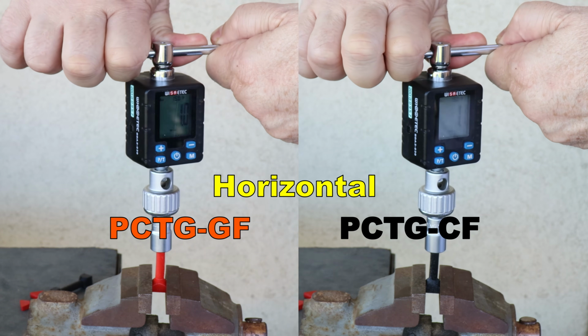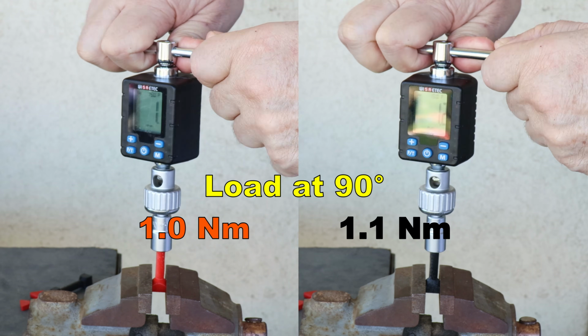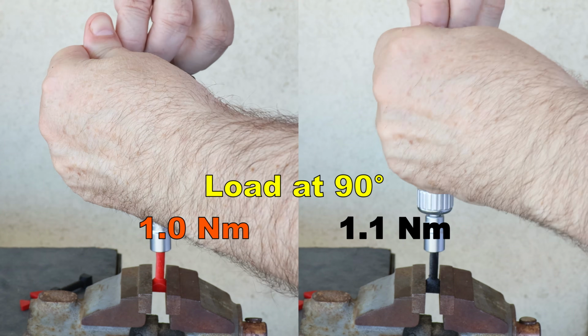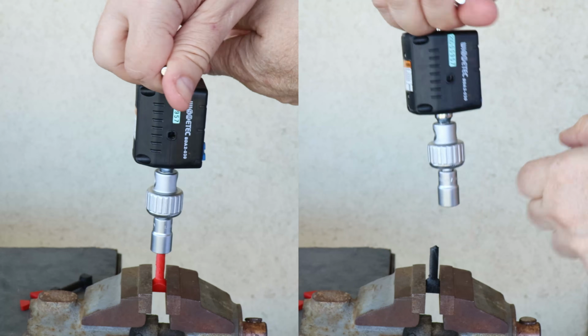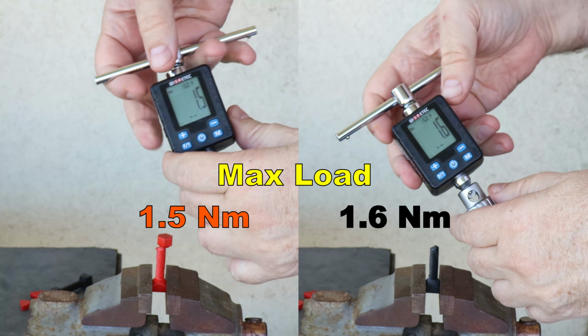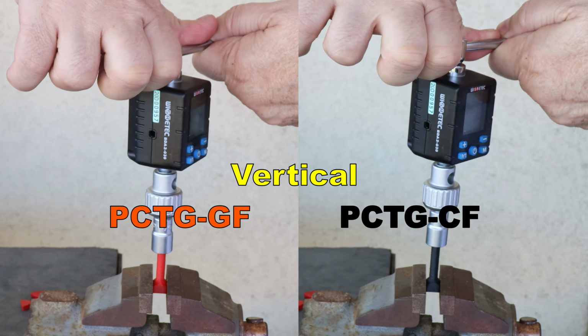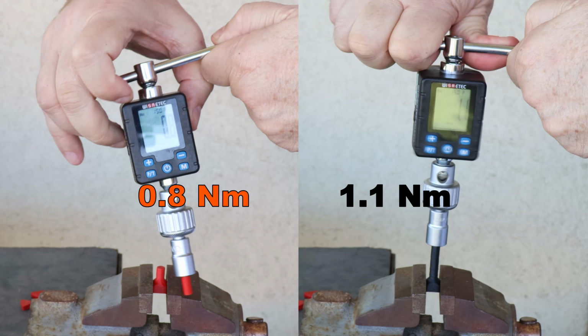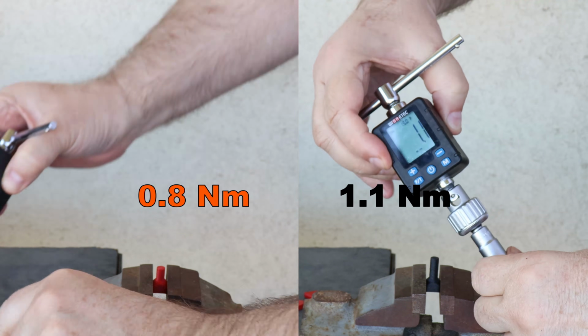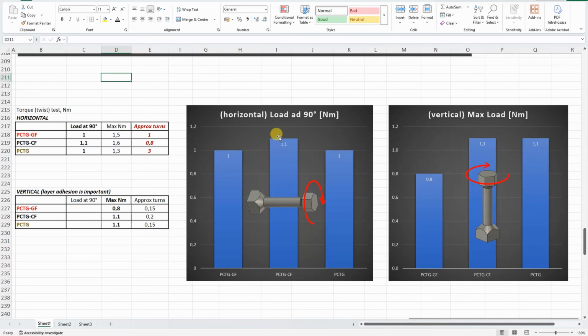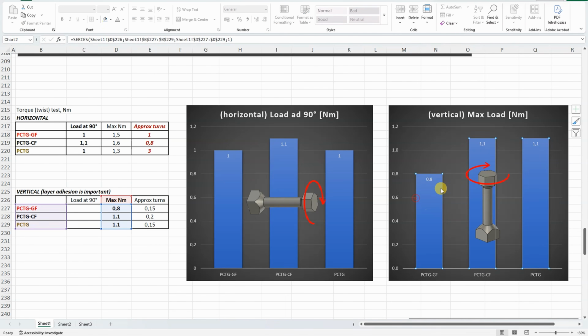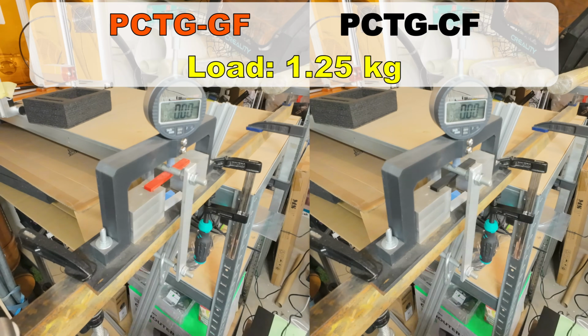Torsion test, horizontally printed objects. 1.1. This was loaded at 90-degree rotation, and now the maximal load. 1.5. Vertically printed specimens. 0.8. The maximal load. 1.1. Printed in horizontal position, loaded 90-degree rotation is very similar in all three cases. Printed in vertical position, only the glass fiber version is a little bit weaker.